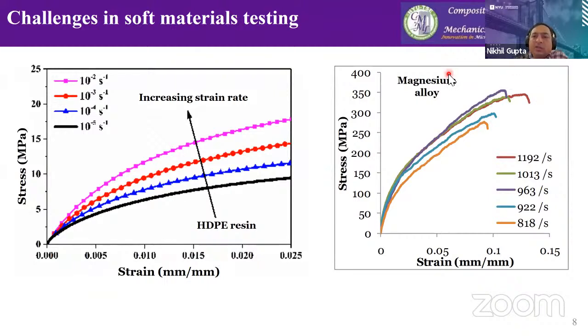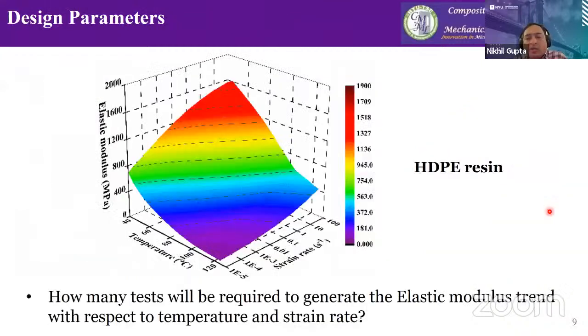There are other materials that have strain rate sensitivity in a very different range of strain rates. And this is where you can see magnesium alloys at 800 per second to about 1200 per second strain rates. So compared to 10 to the power minus 5, this is about 7 or 8 orders of magnitude higher strain rates, but it does show strain rate sensitivity within this range. So we have to figure out test methods that can work and provide us the data over these parameters.